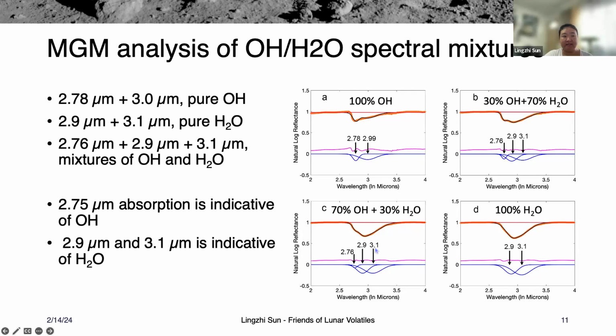our input feature is this 2.75, 2.9, 3.1. We think that 2.75 is indicative of the OH band, which is the well-known silanol structure between silicon and OH. And the 2.9 and 3.1 are the water vibration bands.